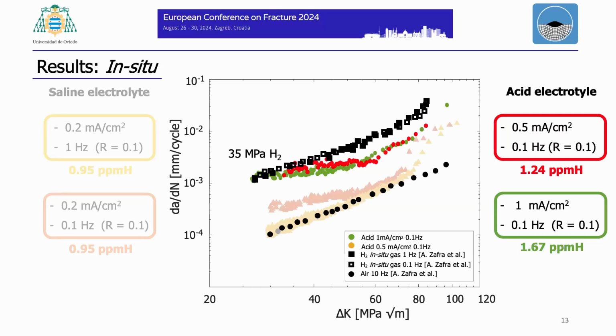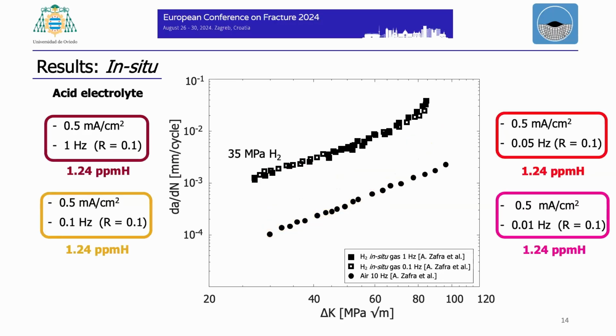So what happened here? We think that the problem is with the surface absorption kinetics, that it seems to be faster in gas and in electrochemical condition it's slower. That's why we can maintain the same behavior during the test. To prove this, we prepared a new batch of experiments using the acid electrolyte, a current density of 0.5, but different frequencies. So we give time to the hydrogen to enter the sample. So these are the 4 conditions that we used.